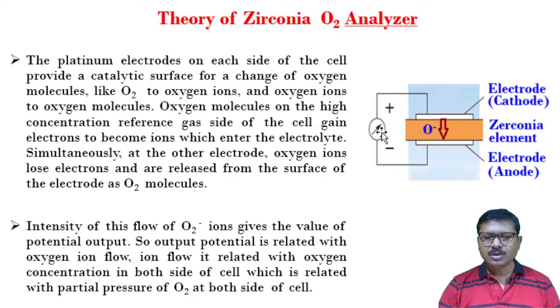Now this output potential is related to the oxygen ion flow, and this oxygen ion flow is related to the oxygen concentration, meaning the difference of oxygen concentration between those two parts, the difference of concentration on both sides, this side and this side, which is related to the partial pressure. This concentration is again related to the partial pressure of oxygen, and here also the concentration is related to the partial pressure of oxygen.